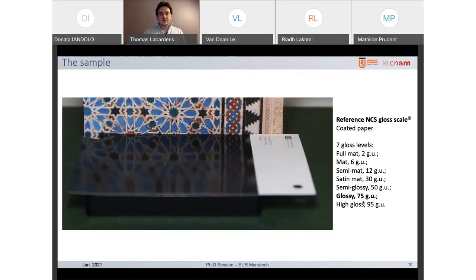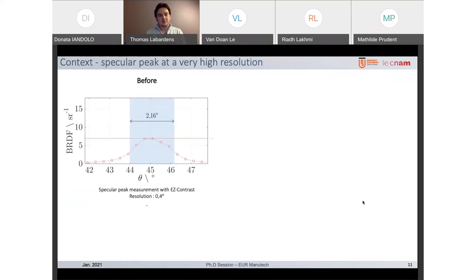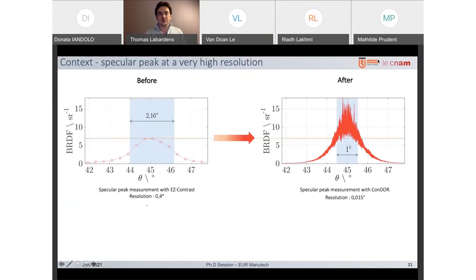This was one of the typical specular peak measurements we could have with the previous device, achieving resolutions of just 0.4 degree. This shape for the specular peak is what we were expecting to have when we began the measurements on Condor. However, this is what we got. We got really strong fluctuations within the specular peak, and at first we couldn't see why we had those huge fluctuations.